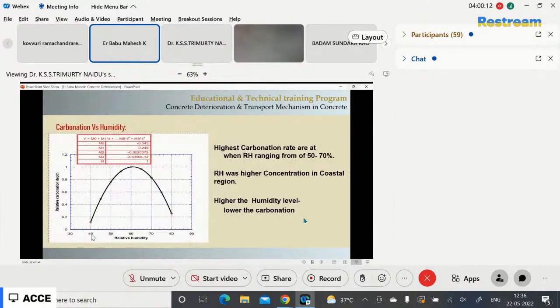At higher RH conditions, the pores in concrete are filled with moisture. In such conditions, it is very hard for gaseous ions to diffuse into the concrete. Hence, the carbonation rate in the coastal region is very low compared with other regions, where in the coastal region the relative humidity would be around 90 to 95. In this figure, we came to know that the carbonation rate was higher at RH ranging from 50 to 70. RH was higher in the coastal region. The higher the humidity levels, the lower the carbonation rate, which I discussed previously.